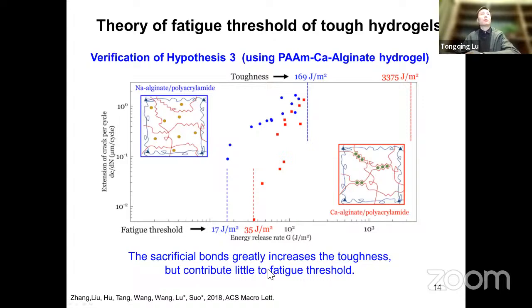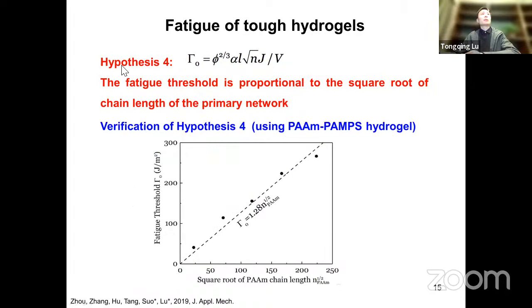So that's our first verification. The second verification is on the chain length, because L, G over V, if just the common bonds, all these are constant. Only the varying is the chain length. So this theory predicts that the fatigue threshold is proportional to the square root of the chain length of the primary network. To verify this, we prepared many different kinds of hydrogels with the same water content, but with different chain lengths, and measured the threshold of all these kinds of hydrogels.